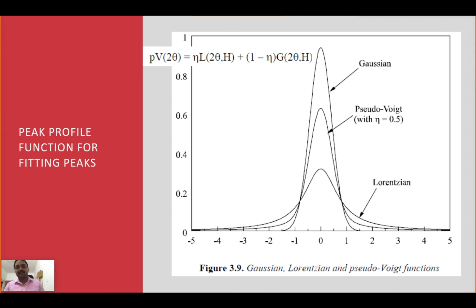Next is, if you are doing any analysis, you are creating theoretical peaks for your experimental peaks, then what function you should select, that also is a problem. Many are proceeding with Lorentzian peak function for producing a theoretical pattern for the experimental pattern. We can call it peak fitting. But now there are problems because Lorentzian peaks are most suited, but some peaks are fitting with Gaussian.